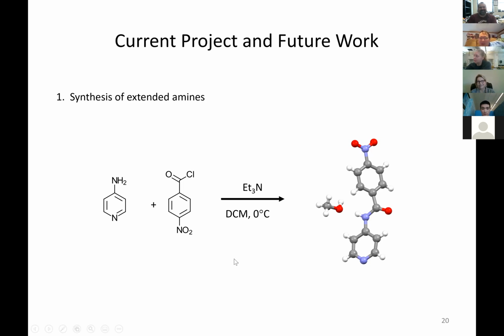So now, once we had synthesized this molecule, we were able to crystallize it. I think Hogan actually was the winner on this one. Generated a nice crystal. We sent it off, analyzed it, and as you can see, this is our crystal structure from this reaction. So here is the pyridine molecule. This is where the amine would be located, the NH2 right here. And this is the portion up here on the top from the nitrobenzoyl chloride.